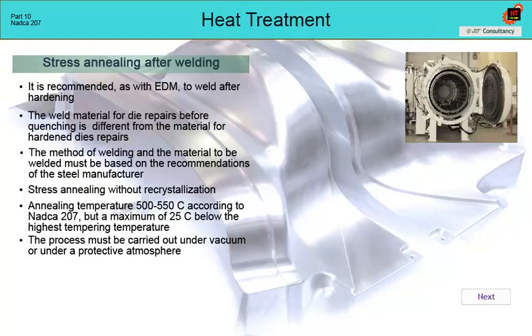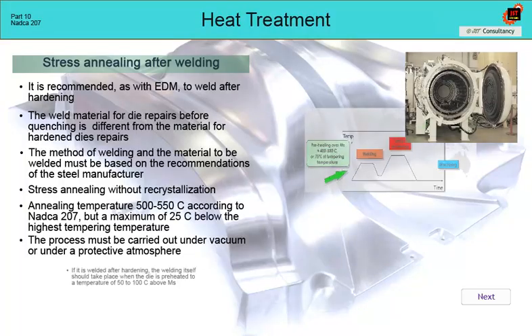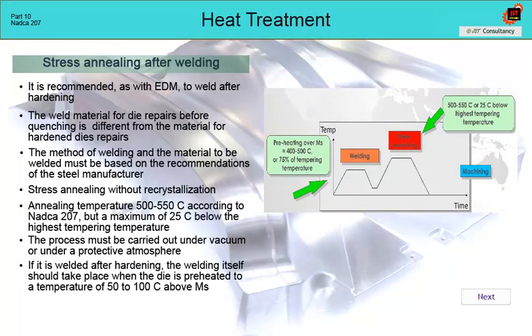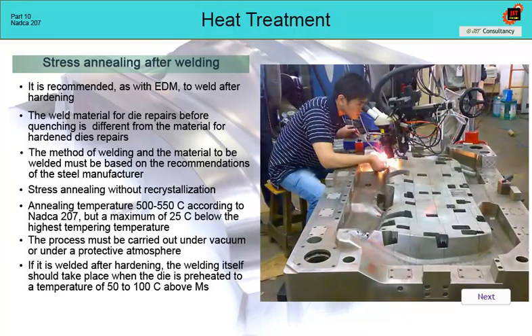In some cases, laser welding is an advantage, but even in this case, die preheating is necessary according to NADCA's recommendations, for example 50 to 100 Celsius above the martensite start line. However, since the thermal radiation from the insert preheated to this temperature is so significant that it prevents the access of the welder, robotic mobile workstations are used for welding.